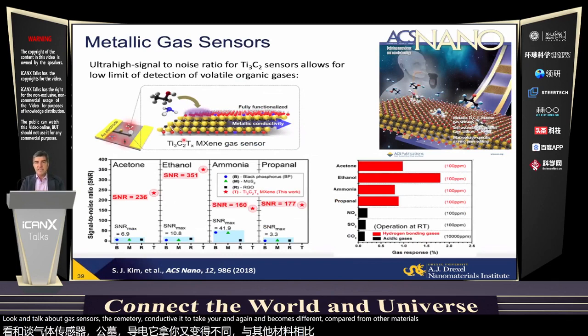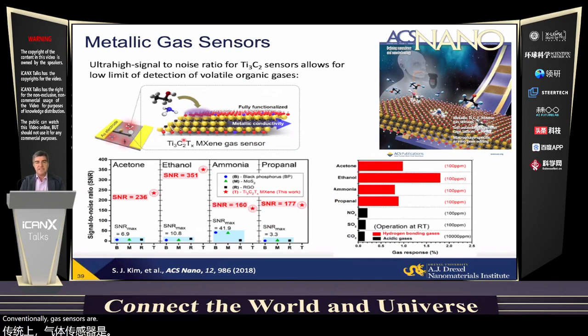Conventionally, gas sensors are semiconducting sensors, where conductivity changes as gases are adsorbed on the surface. They usually require heating up to somewhat elevated temperature, 100, 200 degrees C, to make them work here because of poor conductivity. In case of MXene, changes in conductivity are caused by adsorption on the surface or by intercalation of molecules between MXene sheets.